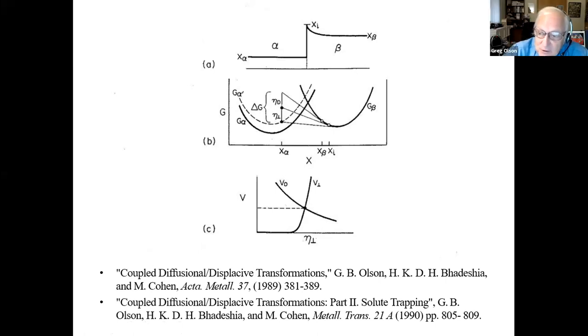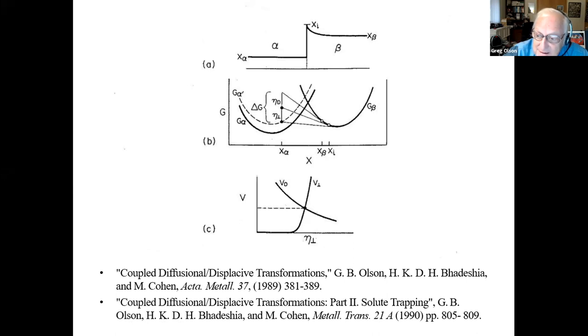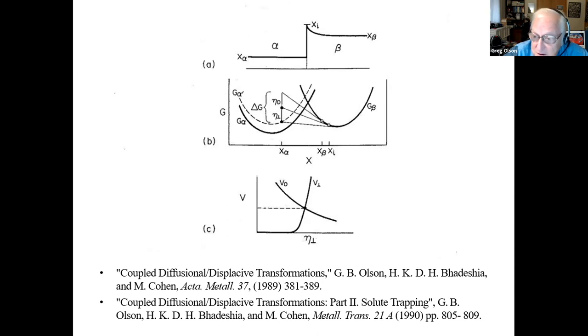We looked at an approach to bainitic transformations, building on the framework we had established for barrierless heterogeneous martensitic nucleation paced by interfacial mobility. With that model in place, we asked the question: if we take the same nucleating defects and embryos of martensite that are stabilized by their defect interaction, and consider at a temperature above MS, would it be possible for a small amount of non-equilibrium partitioning across the interface to increase the driving force enough to assist the glide of that interface? This led to a quantitative exploration of the concept of coupled diffusional-displacive transformation.